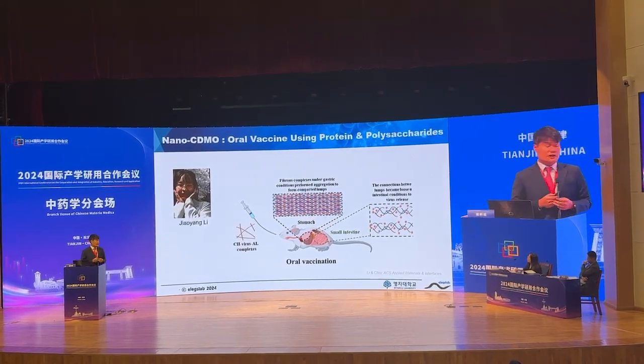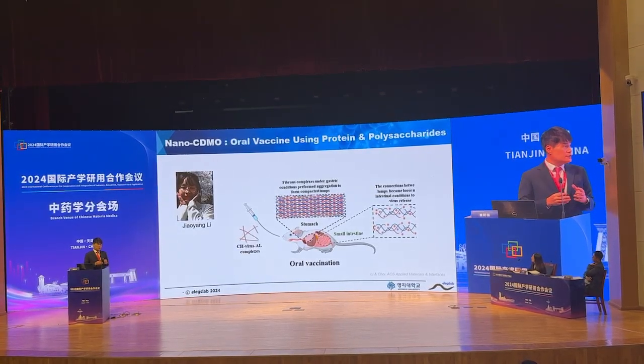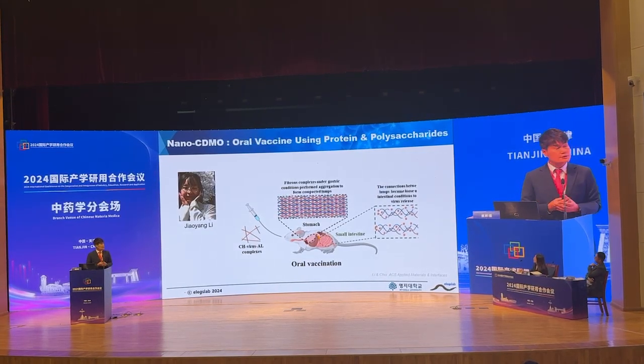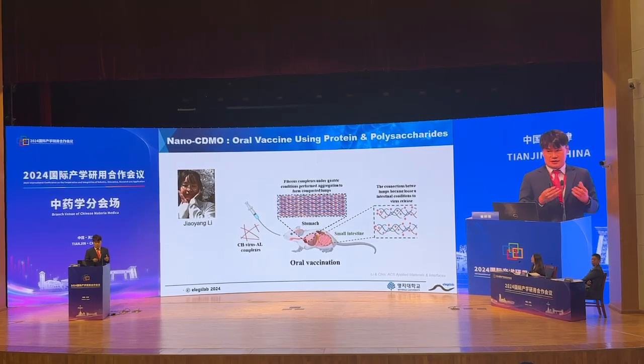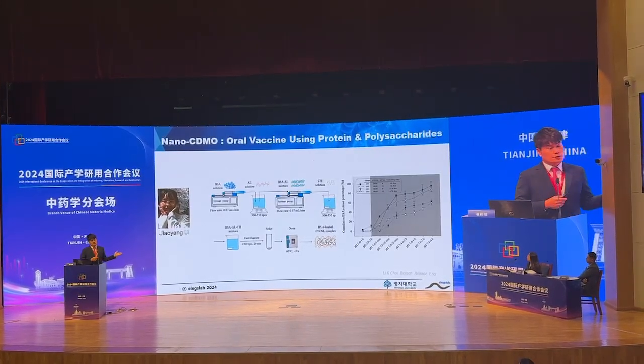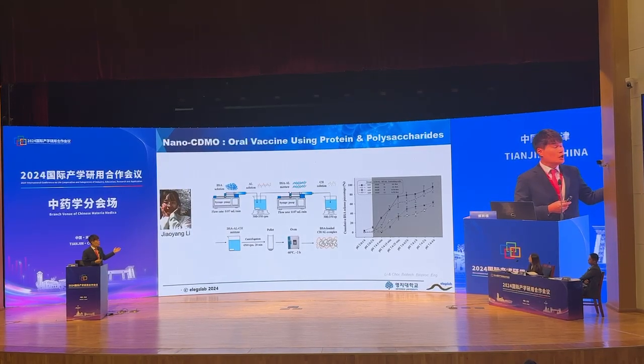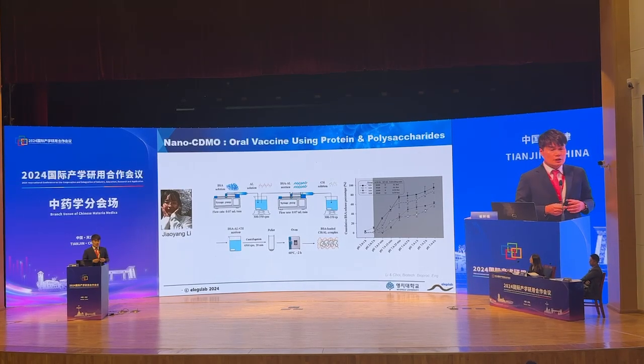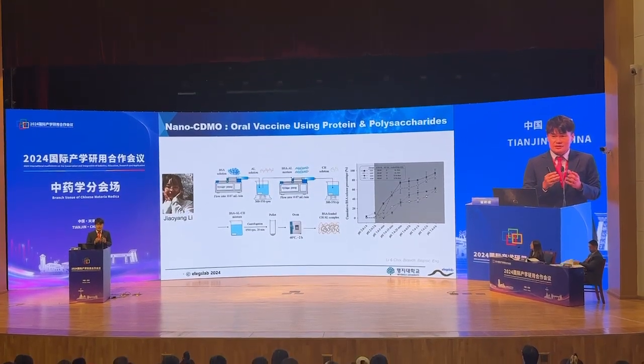My grad student Jiaoyang Li, a Chinese student, formulated this vaccine protein together with polysaccharides like chitosan and alginate, and finally she formulated a nano-sized vaccine. This vaccine is manufactured through a continuous process using the anti-solvent displacement water precipitation method — a nanocomplexation approach — and it has intelligent properties.